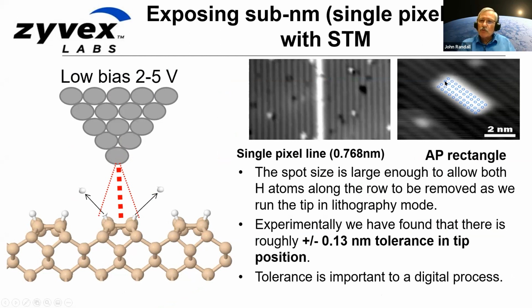If we're very careful, we can make absolutely perfect digital exposures where we remove exactly the number of hydrogen atoms we want to. Turns out we've got a little over an angstrom, plus or minus that, in tolerance away from the center of this zone. So we have some tolerance that we can work with.